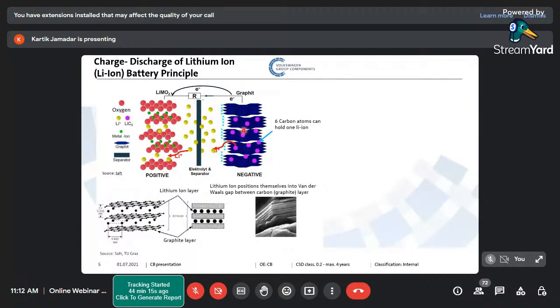So the energy density, which was theoretically about 11 kilowatt hour per kilogram for lithium metal batteries, reduced to 300 watt hour per kilogram, about 2%. So we were only getting 2% of the energy which theoretical lithium could give you. But only with this new idea, lithium ion cell technology was safer and feasible.